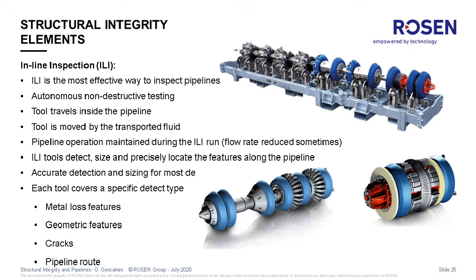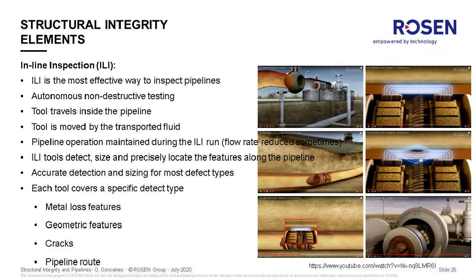Some defects are more difficult to size and detect. So each tool covers specific types of features. The most common are those for metal loss features, geometric features, cracks, and to record the pipeline route. These images are just some snapshots from a video that is available on YouTube that can give you a basic idea of how an ILI inspection works. So you can see the ILI traveling along the pipeline, and this example is specific for the MFL, where you have a magnetic field that is uniform along the wall thickness of the pipeline. But if a discontinuity like a corrosion area is detected, there is a leak in the magnetic field, and that is detected by the sensor, and that is the principle of the detection and sizing of corrosion features.